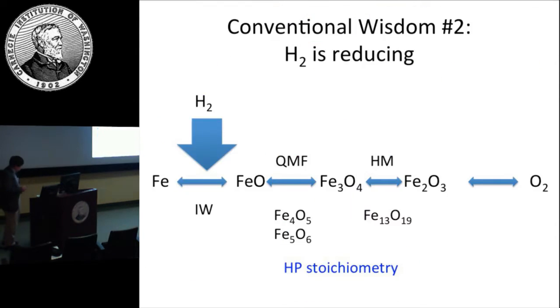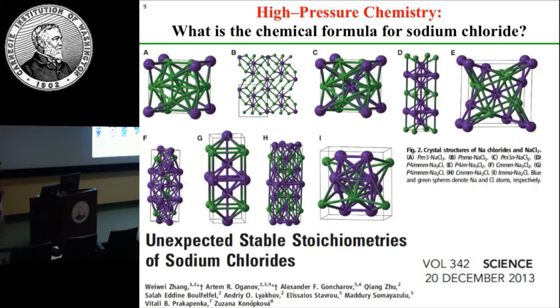But everything here looks like it works nicely with the stoichiometry, and those are all the different ratios of Fe2+ and Fe3+. Like this you have 2 Fe3+ and 1 Fe2+, and this is all 2+. This is all 3+. I just ignore the non-stoichiometry part. Okay. But at high pressure, recently, Alex and the other theoretician like Oganov found that stoichiometry is almost meaningless. It can be changed any way you want with increasing pressure.